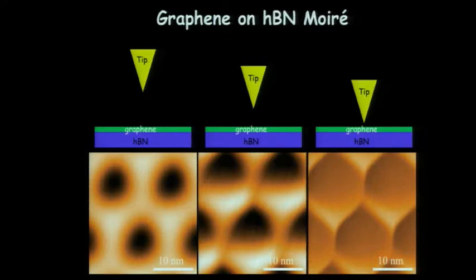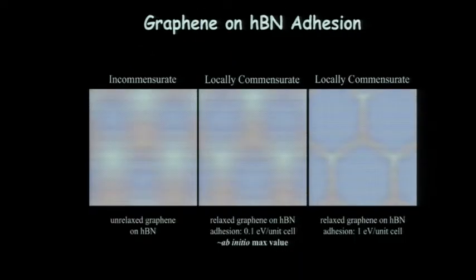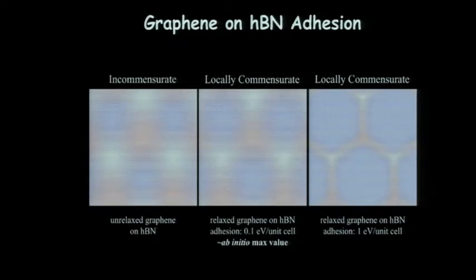This sort of brought to mind some work that had been done on what should happen. These are just calculations of what should be the adhesion between graphene and boron nitride. If you have just unrelaxed graphene, just put graphene on boron nitride, you should have something like this. But if you start to make it locally commensurate by straining the graphene, there get to be changes here. And if you start straining it quite a bit or putting a lot of adhesion, so 1 electron volt per unit cell, you get these very sharp lines here. So the graphene becomes nicely matched here, and there's these domain walls that form on the edge of the Moiré.